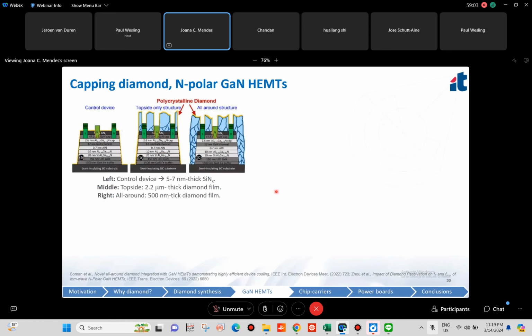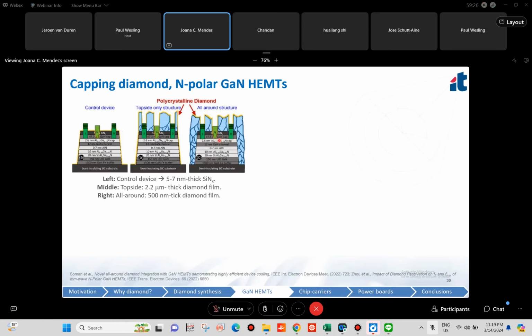A group in Stanford University, they used a different approach. So they used N-polar GaN HEMTs. And in this case, you see that the AlGaN layer or the AlGaN barrier is below the GaN cap. So the channel is formed above the AlGaN layer. And this is good because we can just extract the heat directly towards the surface without having to transport it through this AlGaN layer, which has a lower thermal conductivity.